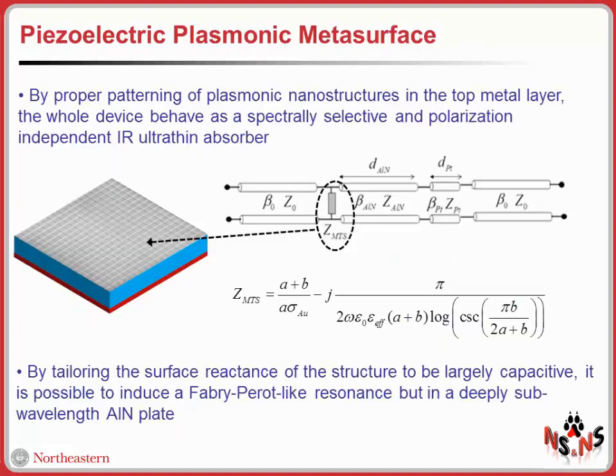This can be done by patterning plasmonic nanostructures. In this example, it is just an array of small patches. These act to tailor the surface reactance of the structure to be largely capacitive, and therefore it can induce a Fabry-Perot-like resonance, but in a deeply sub-wavelength aluminum nitride plate. So even though the thickness is only 500 nanometers, we can absorb radiation at, as I will show you later, for example, about 8 microns.